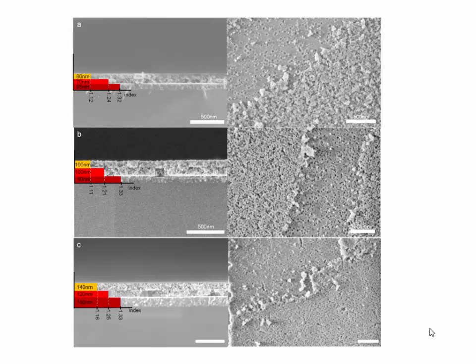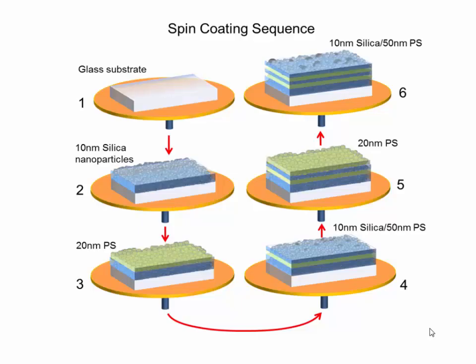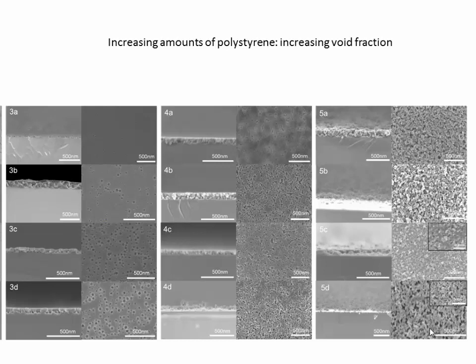This is what I was going to ask also, about what happens with the mechanical stability of these films when you have a 90% porosity. Yeah, it's actually not very stable. This is like an aerogel. When we actually made our multi-layer coating, we didn't try to use the lowest refractive index material, because we discovered that it's very hard to achieve that lowest refractive index on the multi-layer structure.